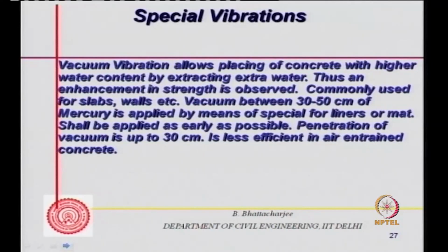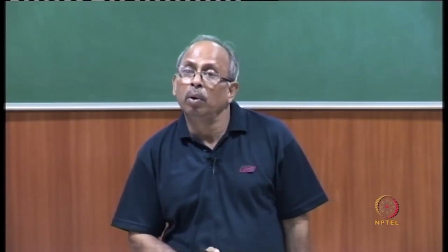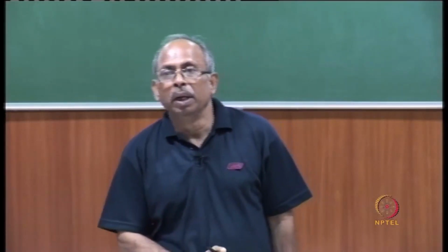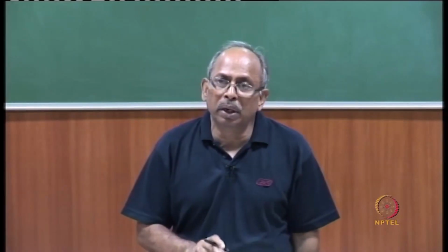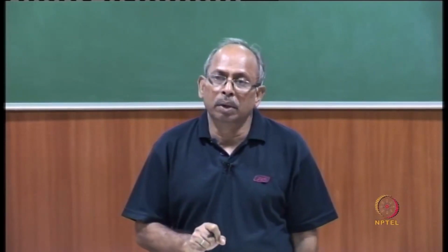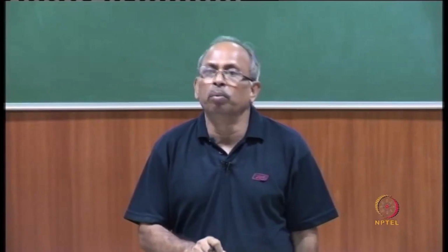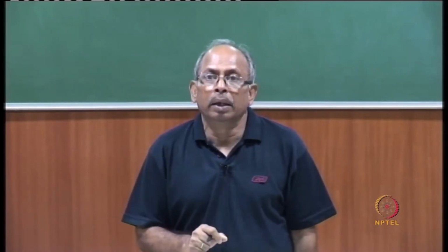So placing concrete with higher water content and then extracting the extra water, strength is improved. It is commonly used for slabs and walls. A vacuum between 30 to 50 centimeter of mercury is applied by means of special liners of material which allow water to come out, but the solids will be kept. So you have a mat placed on top of the concrete, and then water is evacuated out through the vacuum.